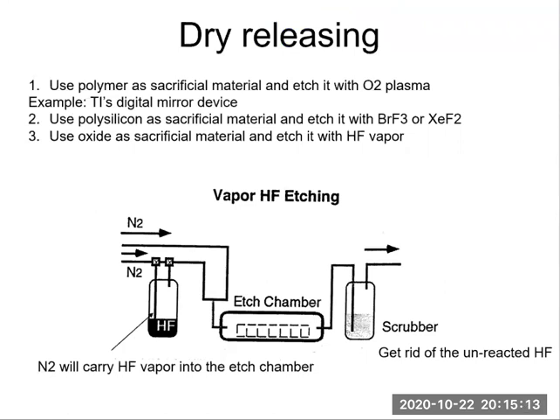Dry releasing. Obviously, we can use dry etching methods to etch the sacrificial layer and avoid stiction, because stiction is initiated by the capillary force. Right? If the etching process is completely dry, then there will be no capillary force and no stiction. So this is another anti-stiction method. With dry etching, no liquid is involved.